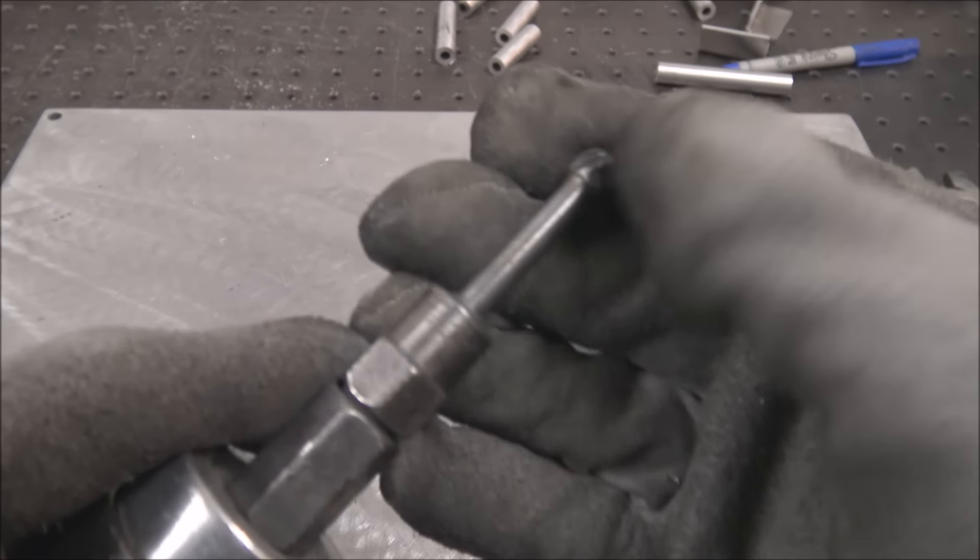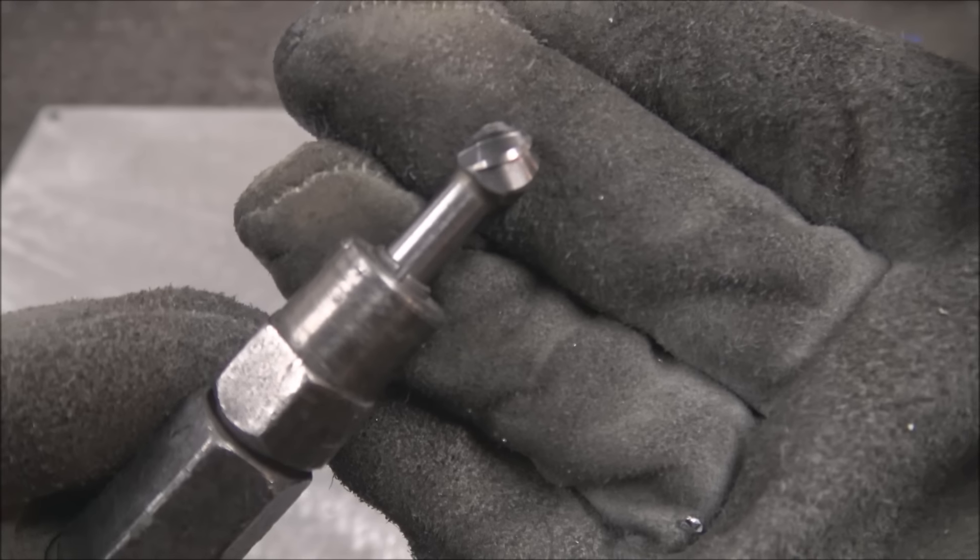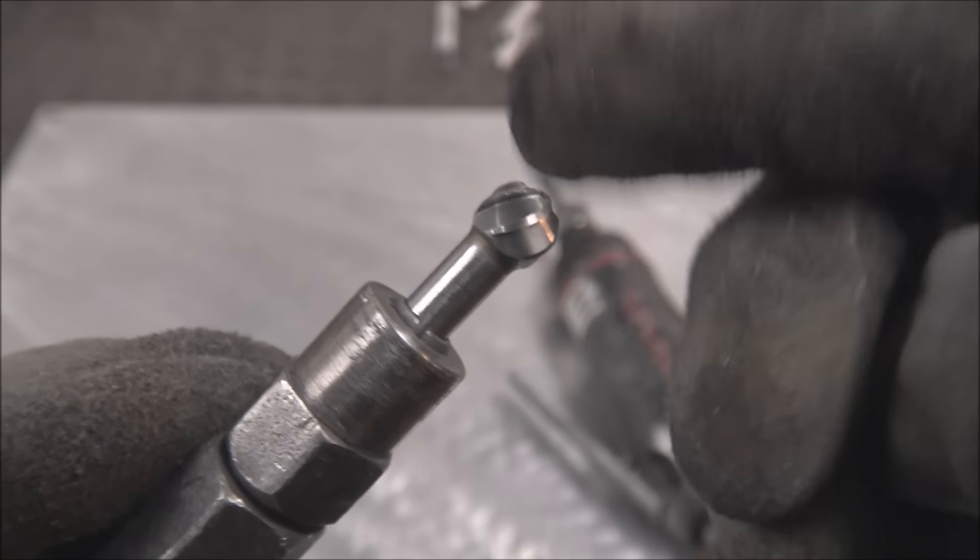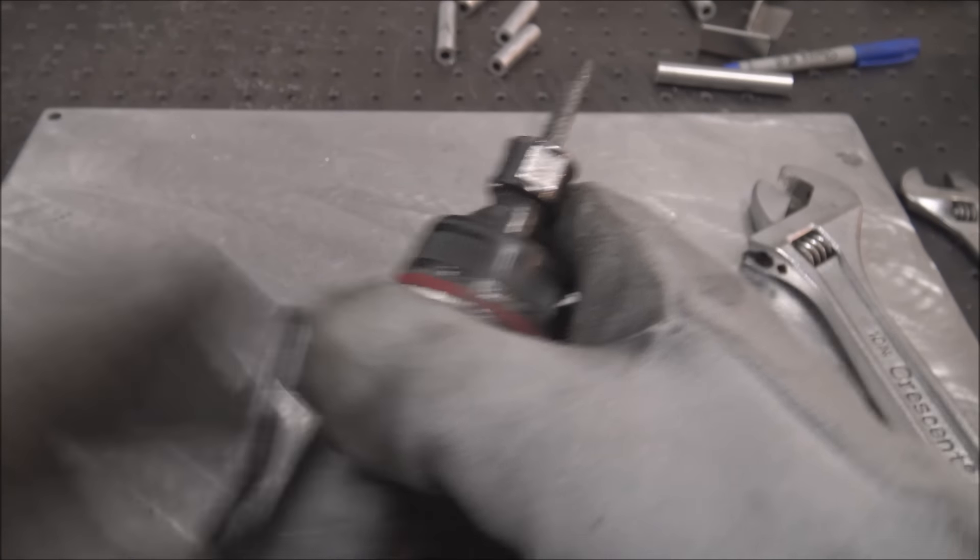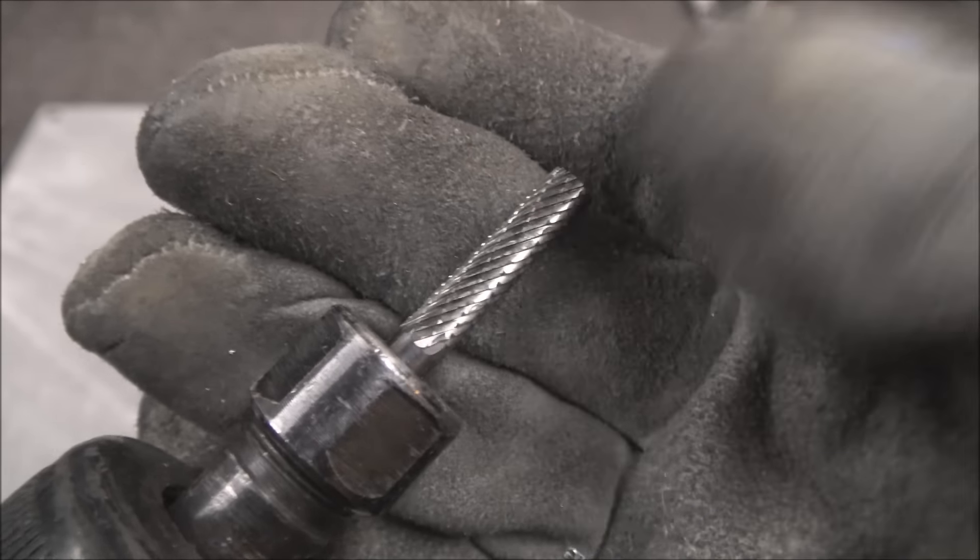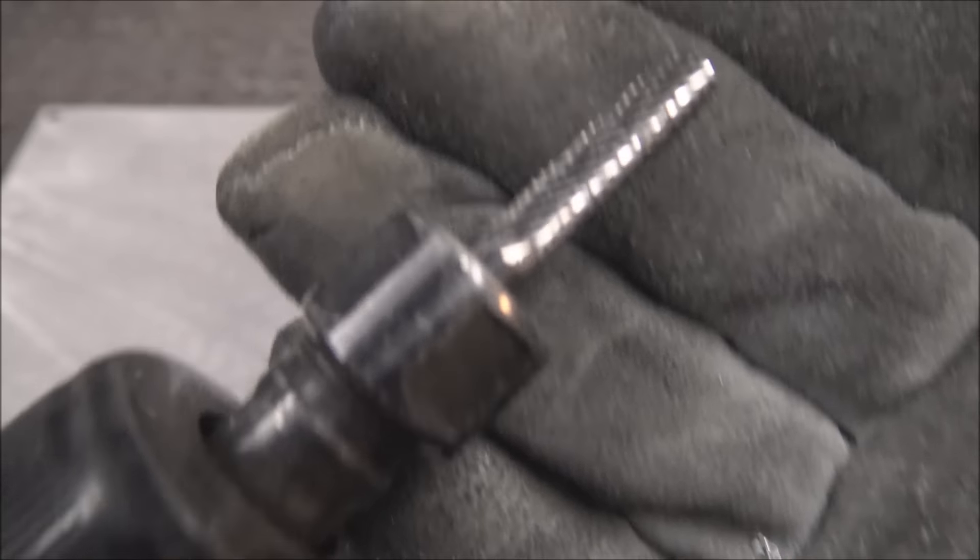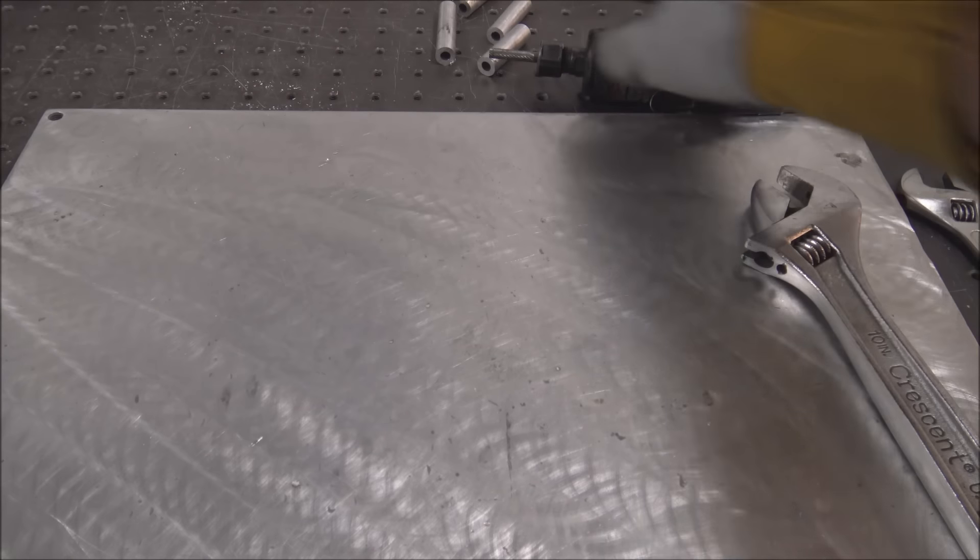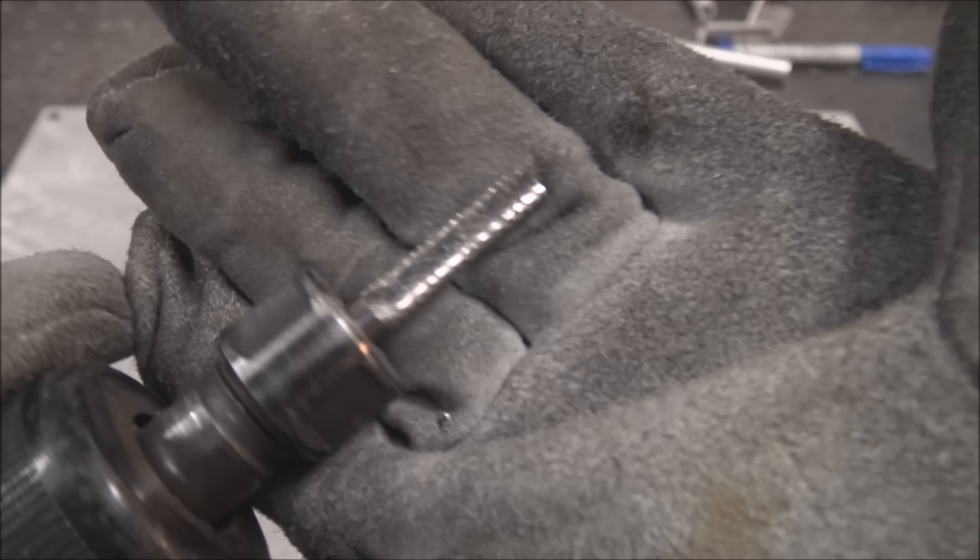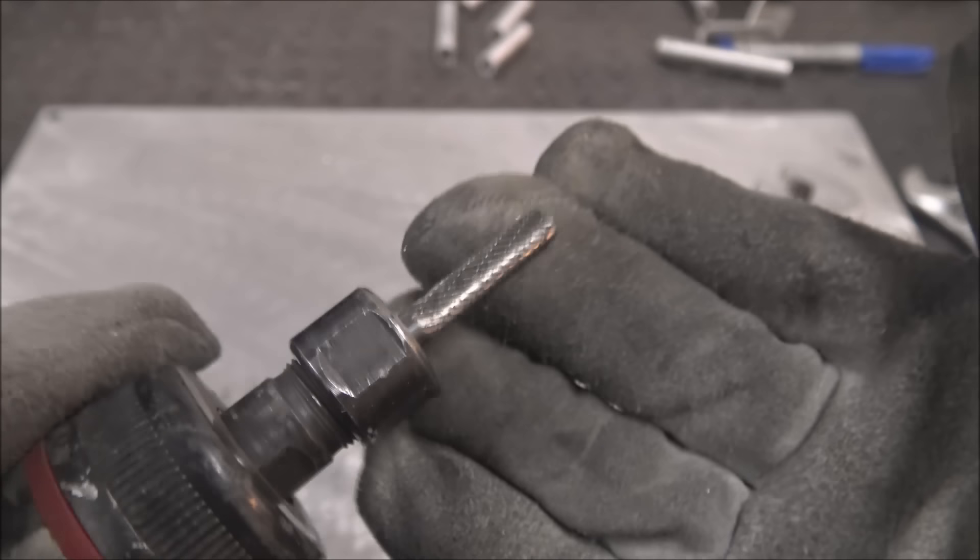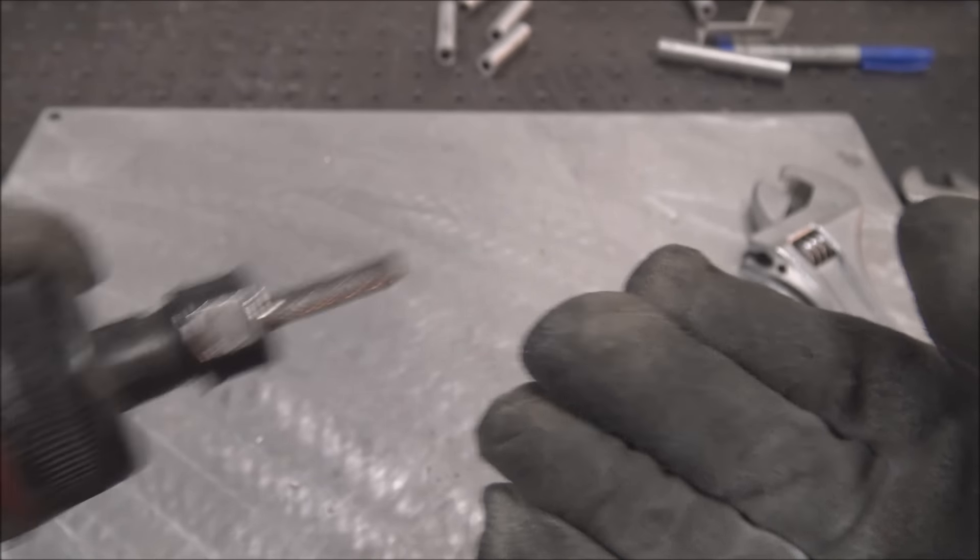For this type of work, aluminum removal, I like these little carbide burrs with the wide flute spacing. I'll put a link in the description below. And not these ones, these ones work great for steel and stainless steel. But for aluminum, they clog up too quick, they heat up and clog up. And you can get these to work, but you've got to put coolant in them like WD-40 or some lubricating fluid. But then you end up packing that into your material that you want to weld. So doing this type of stuff, if possible, I like to do it dry.